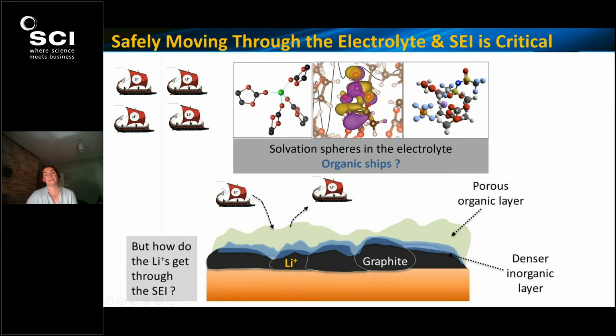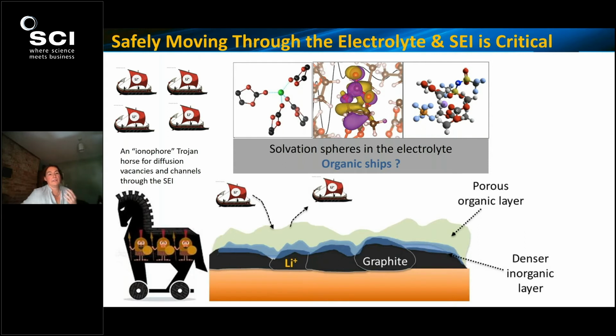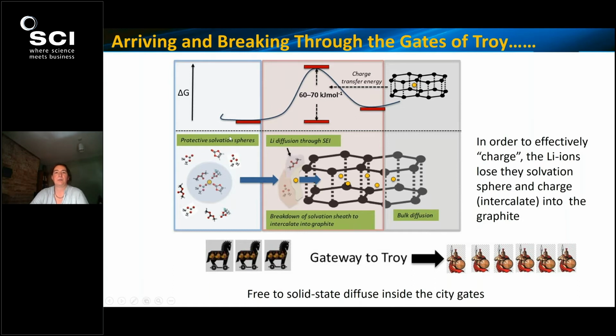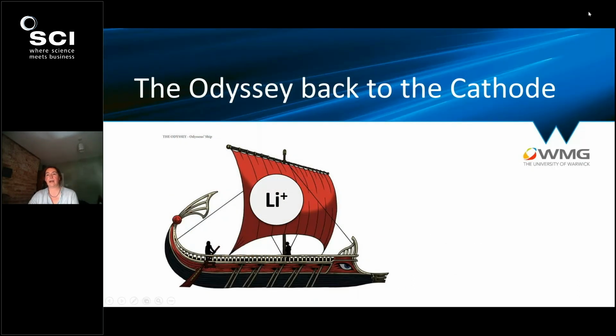But they still need to get through the SEI safely. And this is where we have advantageous ionophores, or sort of ionic Trojan horses, and diffusion vacancies and channels that can get the lithium ions through so that they can get into the intercalation of the anode material. And so arriving and breaking through the gates of Troy, which you can see depicted energetically here. So losing the solvation sphere means they can effectively charge into the graphite through the gateway to Troy, or the SEI layer, in order to then intercalate into a maximum diffusion space so they can fully get into the graphite particles. That, in a nutshell, was the siege and the Battle of Troy.